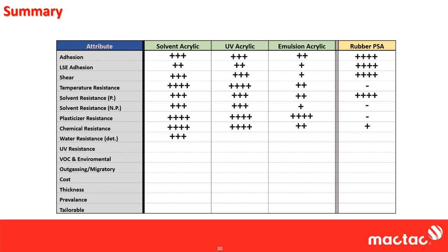And again, kind of like the solvents, polar, non-polar, acrylics can swell. The solvent and the UV acrylics, they won't dissolve, but they can swell. Emulsion acrylics actually do pretty good with water. It seems like an oxymoron, but it's the same concept of paint. It's pretty complex, but once they're dry, they actually don't necessarily want to redissolve. At least modern day emulsions are like that. And rubber PSAs, again, because of the polarity, pretty good, very good.